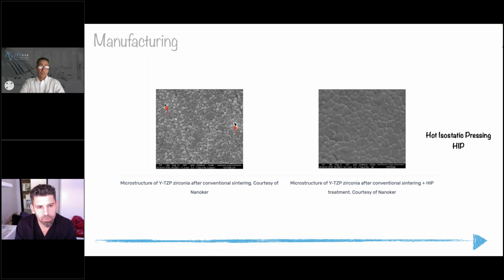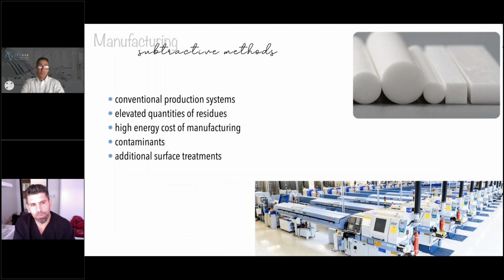Once this material, once the zirconia has been pressed together, the rest of the manufacturing is by subtractive methods. So we obtain these zirconia rods, and then it follows the conventional production systems like titanium implants follow, for example. These rods are milled. There's an elevated quantity of residues. It's a high energy cost of manufacturing. There's contaminants that can be introduced.